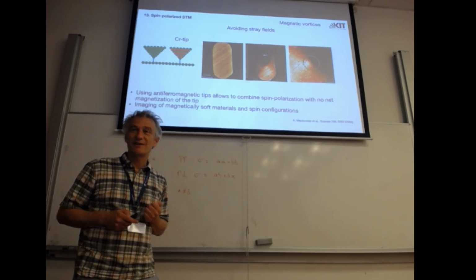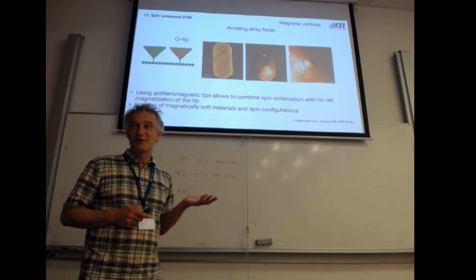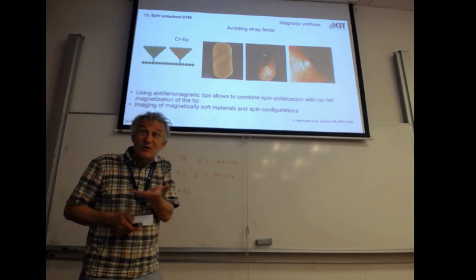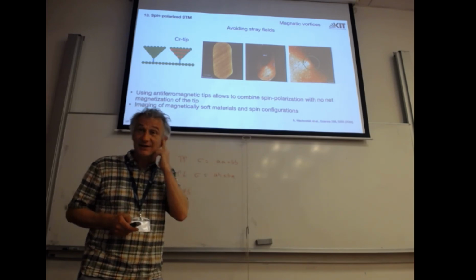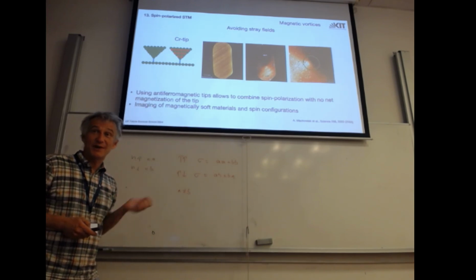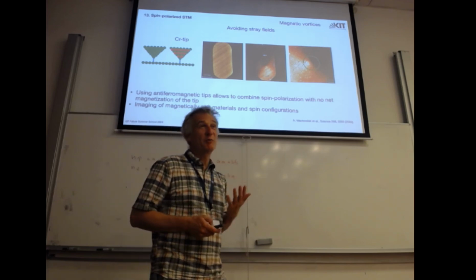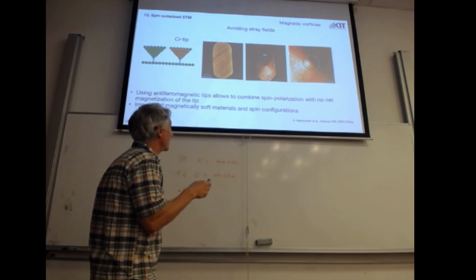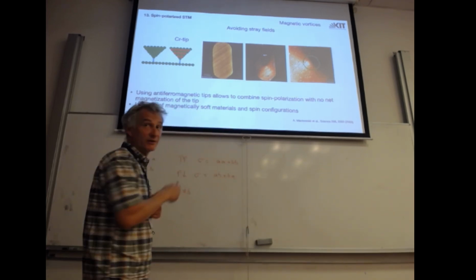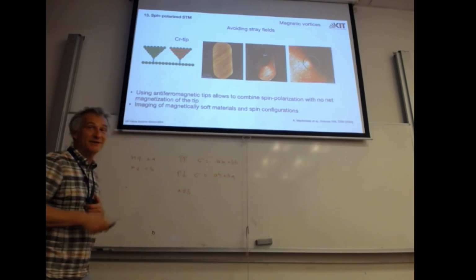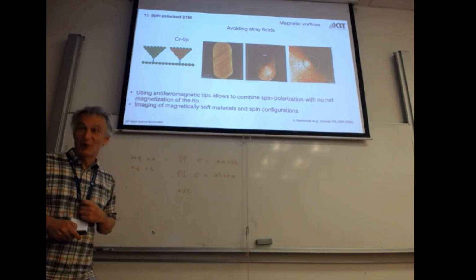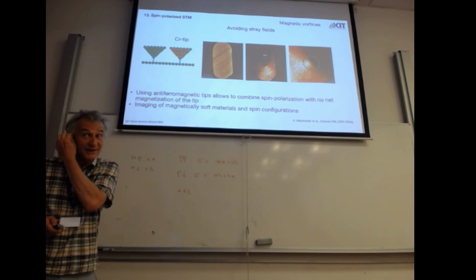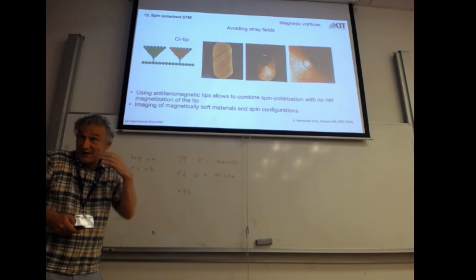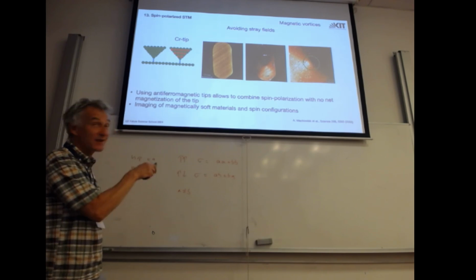And if you switch off the laser, there is no spin polarization. So actually you can, by light, switch the spin polarization of gallium arsenide on and off. This works. This has been done in Japan. The only problem is you have to shine the light here into the tunnel junction. And this is a ferromagnet, and the ferromagnet also has a different absorption coefficient for left and right circular light. So your light intensity will also vary just because the sample absorbs it differently.